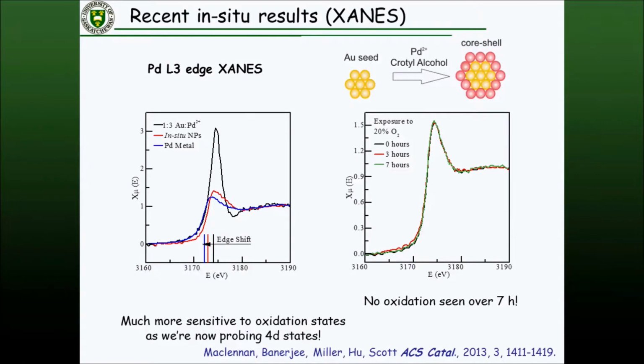As soon as you add the crotyl alcohol, the very next spectrum, the red one there, shows a loss of intensity because you've filled the 4d orbital by reducing the palladium in the system. What's interesting is that the 3rd, 4th, 5th, 6th spectra all look exactly the same as that red one. It never actually approaches pure palladium metal. It's always slightly higher in intensity and slightly shifted in energy compared to pure palladium metal. This is evidence of a little bit of a 4d deficiency in palladium on the gold.